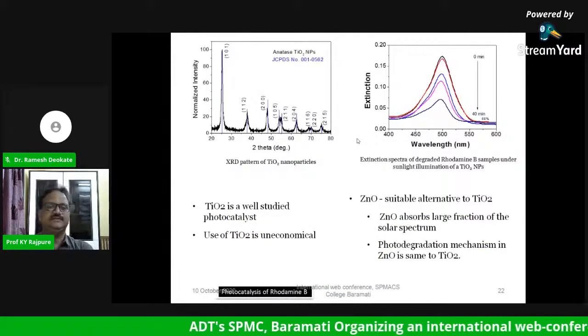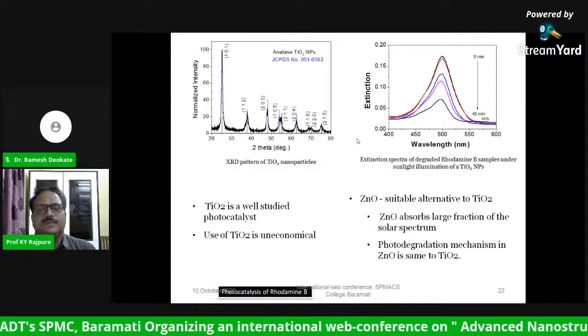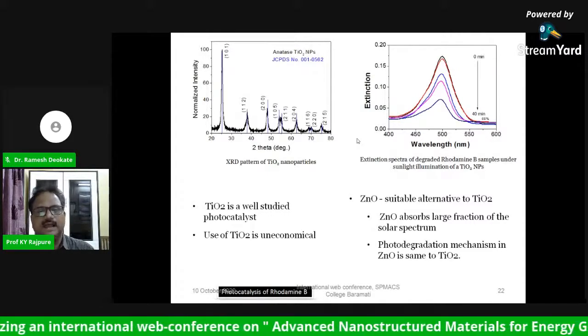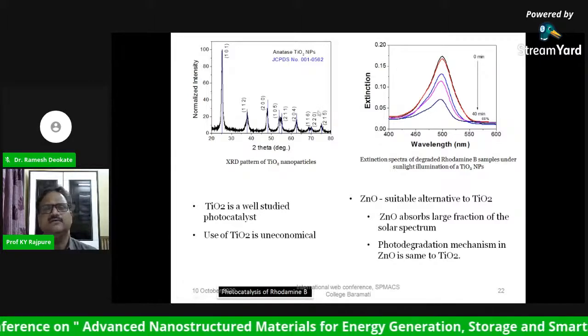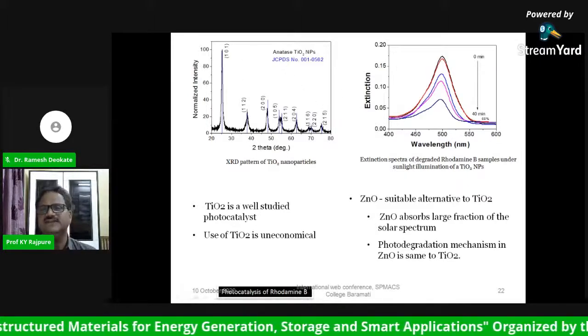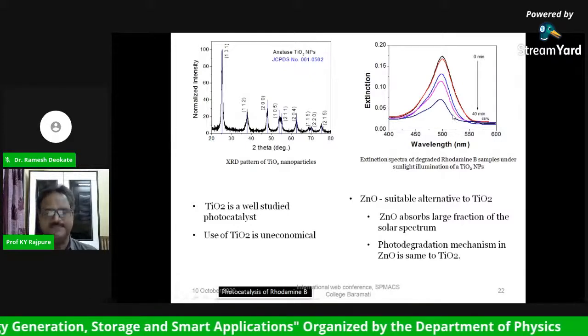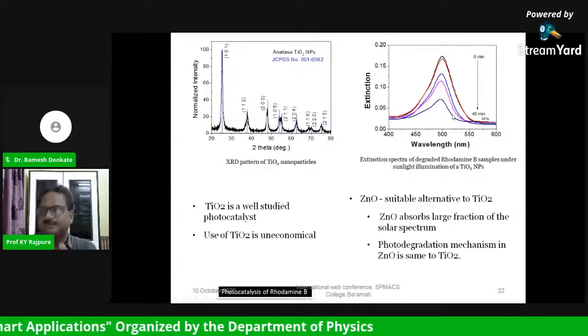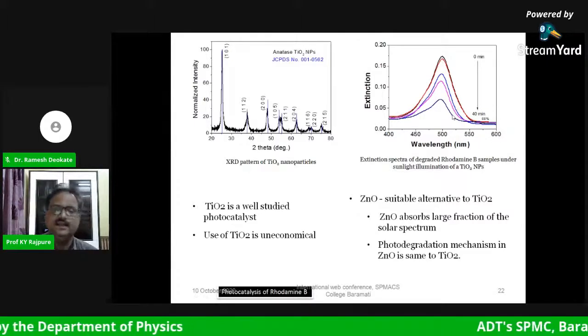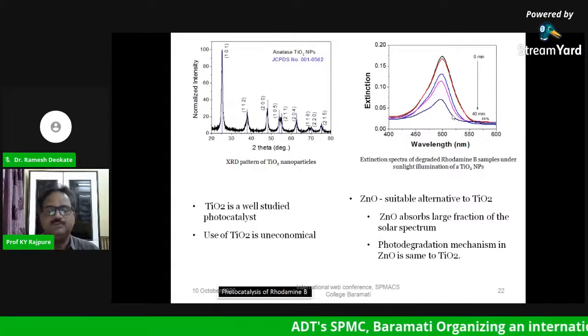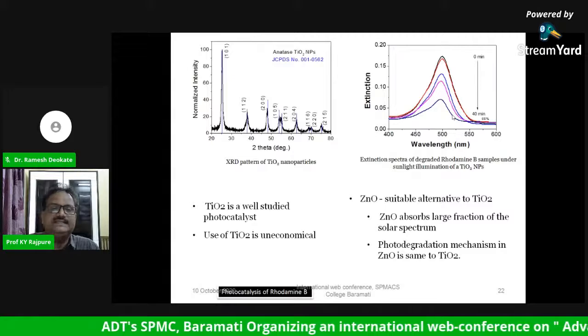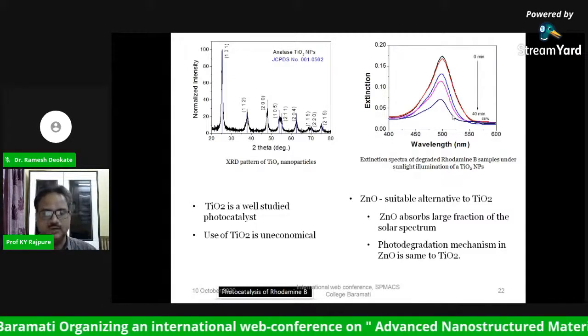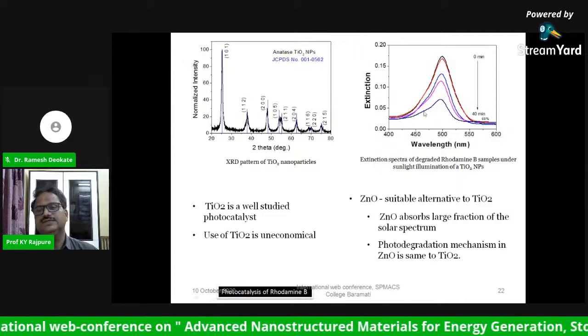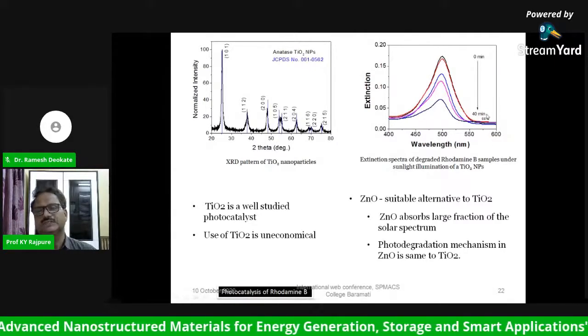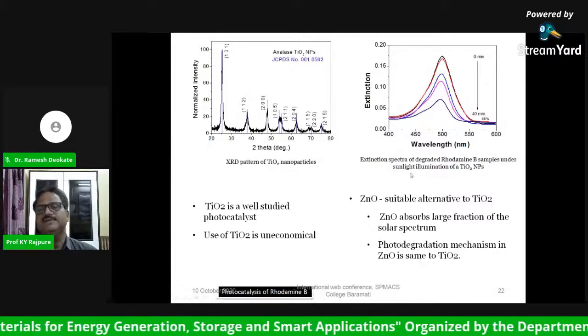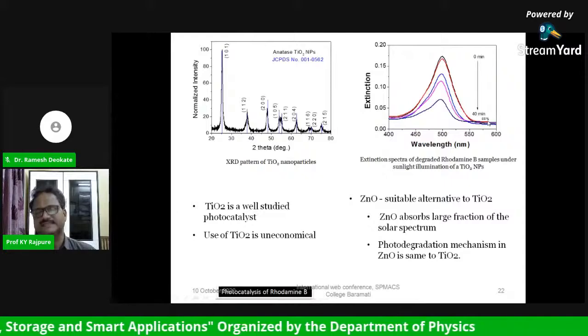TiO2 is extensively studied as a photocatalyst. It is well studied. Therefore, we prepared TiO2 powder, and it was observed that this powder was in the anatase phase. We degraded rhodamine B, which is one of the test pollutants. We took some organic chemical and deliberately added it to pure water, so the water became impure. This impure water was made pure by putting in the TiO2 powder, which we prepared by a chemical route, and we saw that within 40 minutes or so, this impurity, rhodamine B, is removed, more than 60% of it.